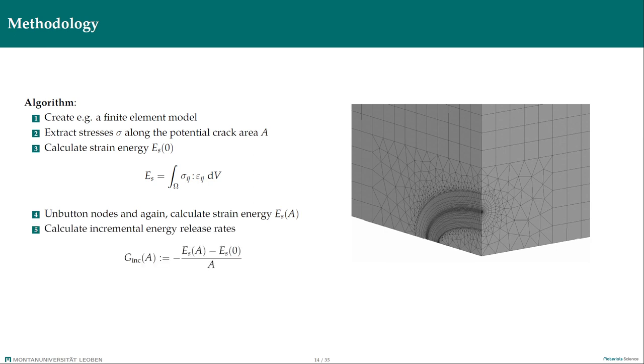In the post-processing, we calculate the differential or you can call it tangential and then also with incremental or you can call it secant energy release rate. The latter one, secant energy release rate, is between state when there is no crack and the state where there is finite size crack, which is the determinative factor in the coupled criterion.